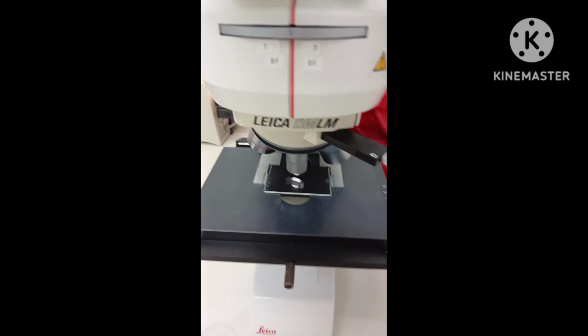Here again, on the microscope, the same sample. After some more time of polishing, you can see now that the surface is quite better. I will change the lens to a higher magnification. Here you can no longer see the scratches. For example, if you are trying to study the pores, this is enough to do so.